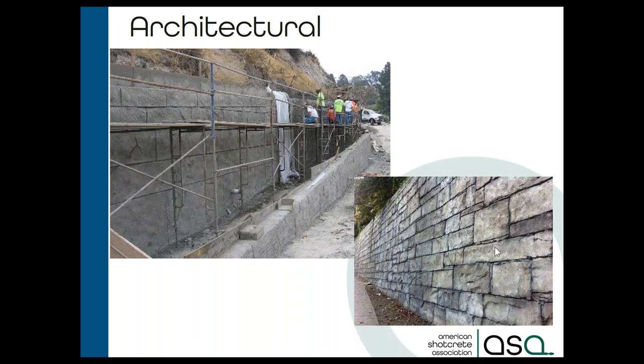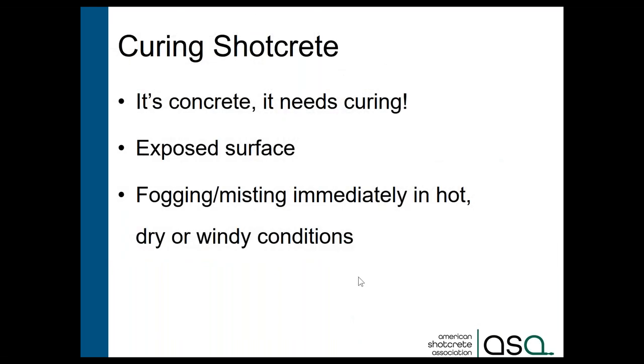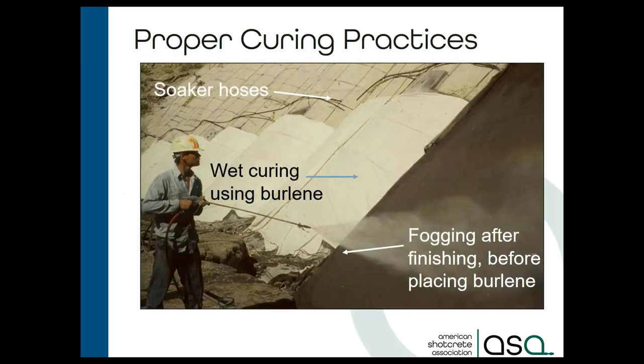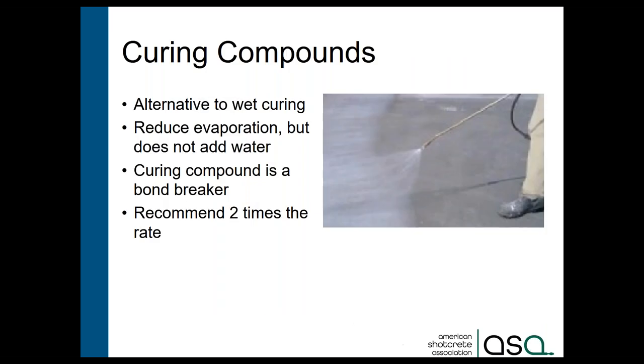Rock scapes by shotcrete artisans — you may drive along highways with retaining walls or shotcrete made to look like rock walls. It is concrete when we shoot it, has an exposed face, and must be cured. We recommend fogging or misting in hot, dry, windy conditions — and as a normal course of action to keep the surface from drying out and getting early-age plastic shrinkage cracks. Ideal is water curing. Sometimes you're shooting overhead and can't water cure, so we recommend a curing compound applied at twice the normal rate to get a good seal, because when curing with compound the only water for hydration is what was originally in the low water-cement ratio mix.